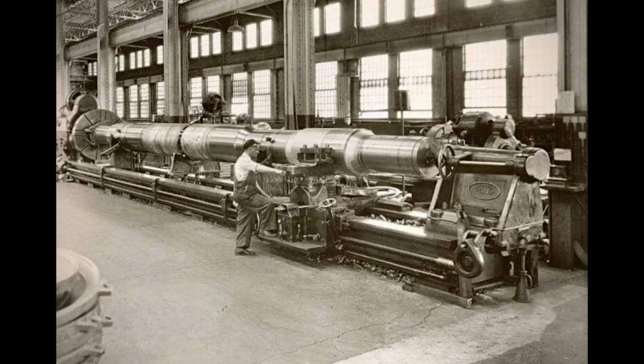The operation had to be fast, before the steel cooled and lost malleability. Too slow, and the steel wouldn't flow into die details. Too fast, and the force would crack the die. Springfield Armory workers developed a rhythm, placing hot bars, dropping the hammer, extracting the forging, all in synchronized movements that looked like industrial choreography. The forged receivers then went to heat treatment.